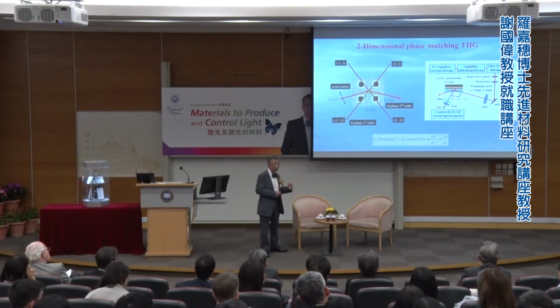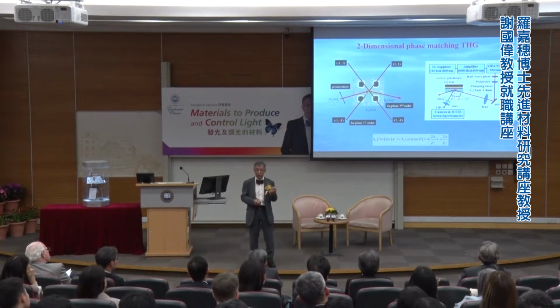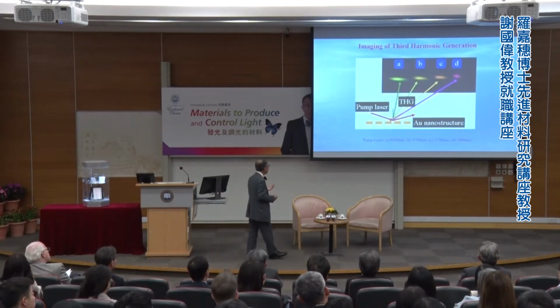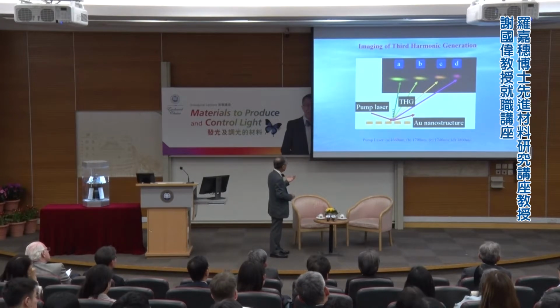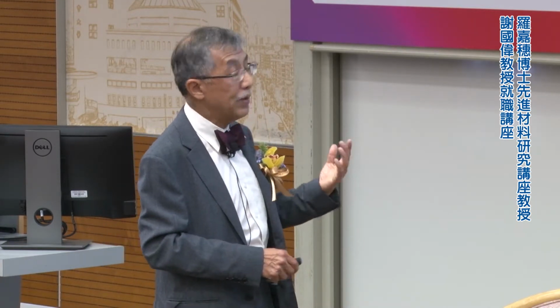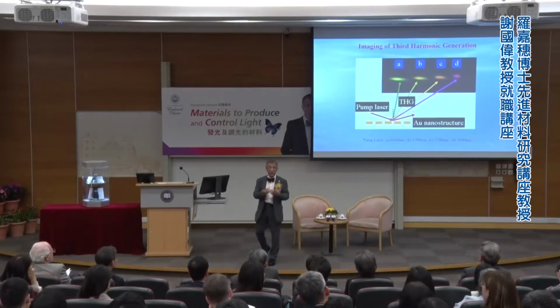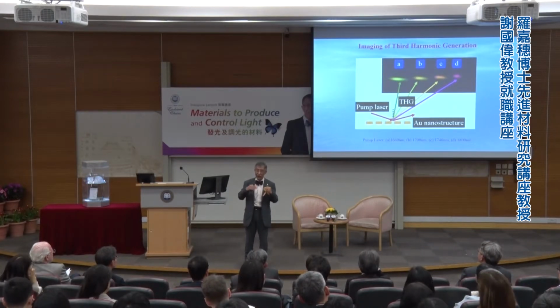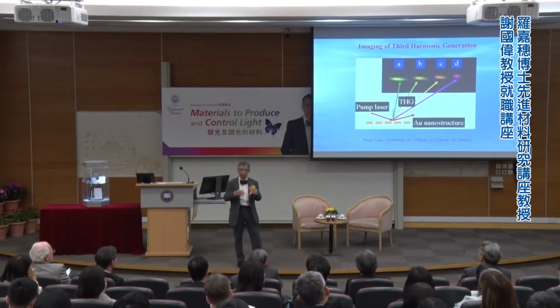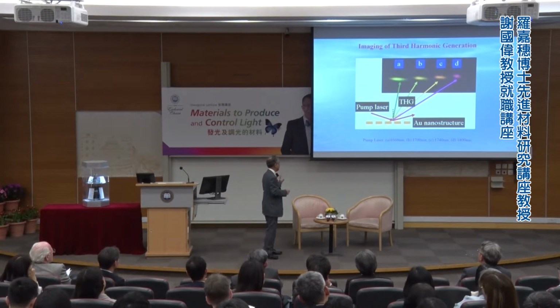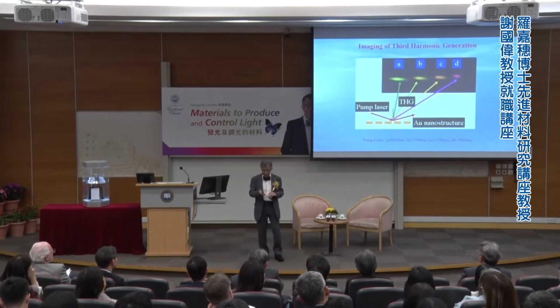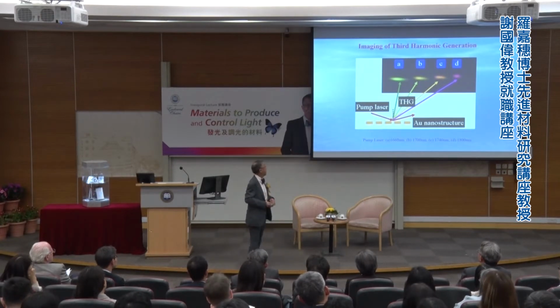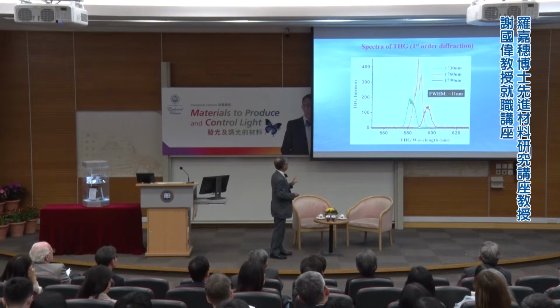That means that using infrared light, you can actually get the shorter wavelength of visible light. And this is what you see: we use the near-infrared wavelength from 1,600-odd nanometers to 1,800 nanometers here, which we can't see, but then you can see all different colors coming out. And that actually gives you a cheaper way. Nowadays, you still have to use crystal, but eventually we hope that we can perfect this, so that we can have a cheaper and more efficient way of producing different colors. This is the spectrum of that.